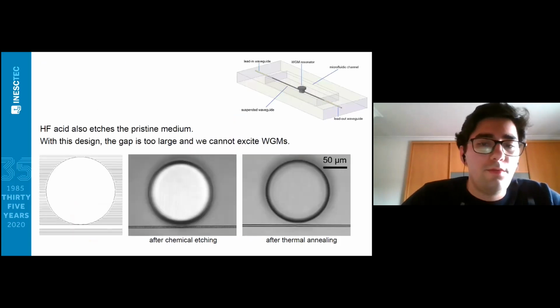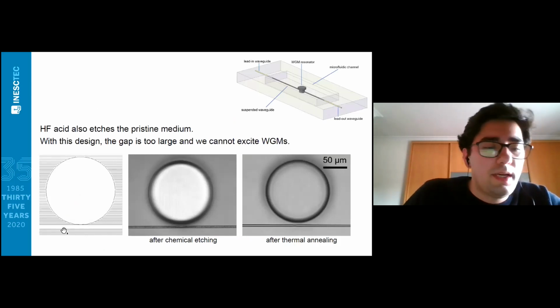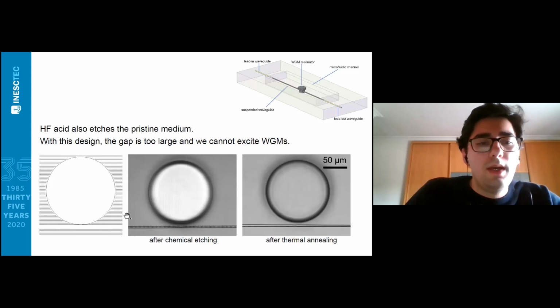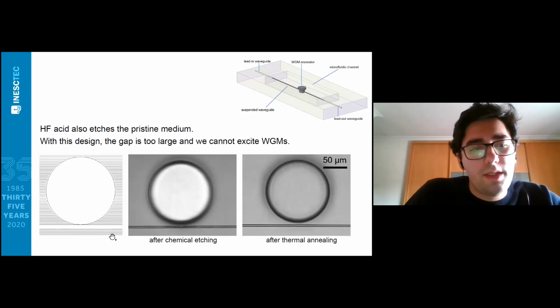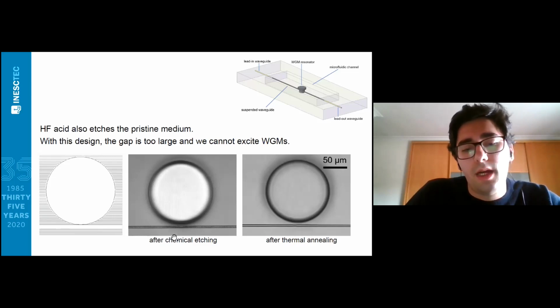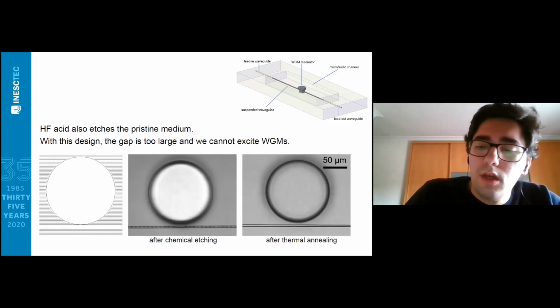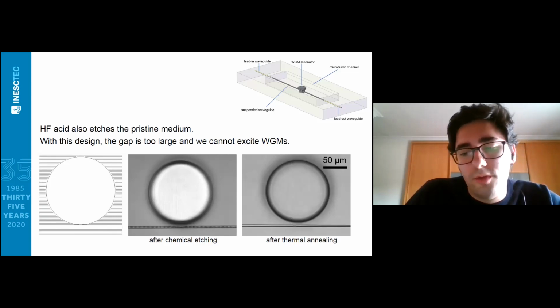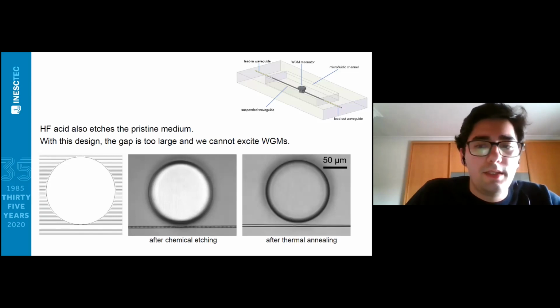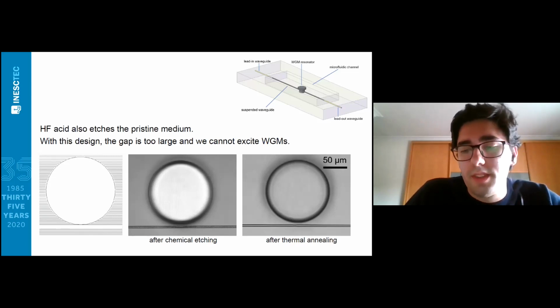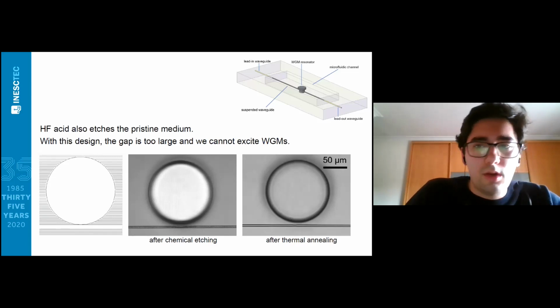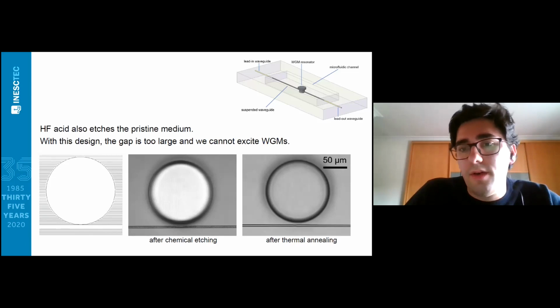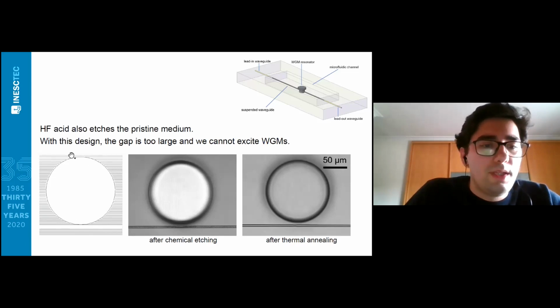However, if we go for a configuration where the waveguide is initially designed tangent to the microdisc, as shown in this picture, where each of these tracks corresponds to the path of the laser beam, then because the HF acid can also etch through the pristine medium, after etching and after thermal annealing, we end up with a gap of around 2 to 3 micrometers in between both structures. And this gap is too large and prevents us from exciting whispering gallery modes. So in order to realize this device, we need to also alter the way we design it.